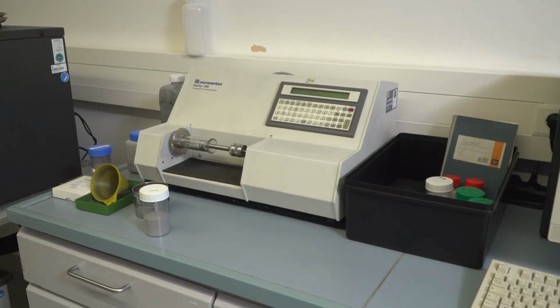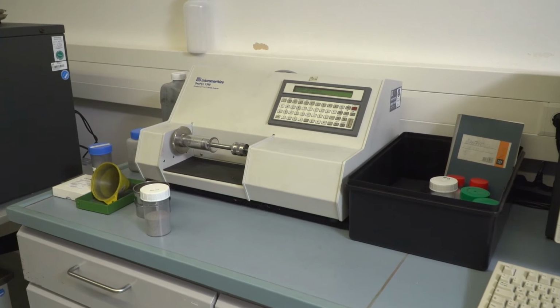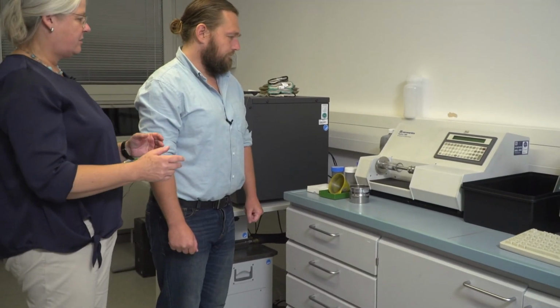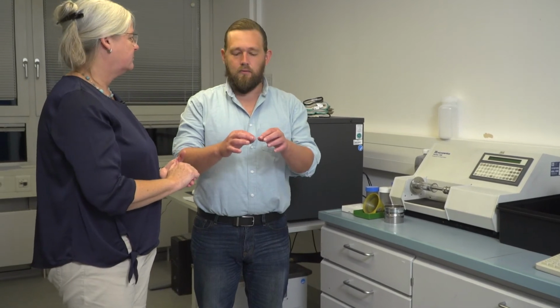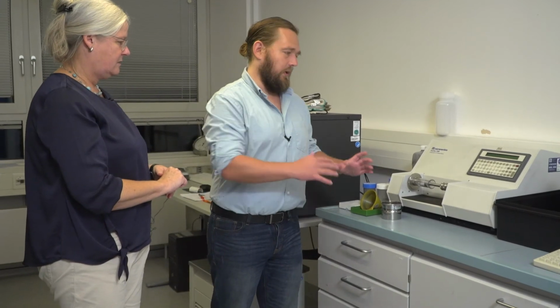So what does this device do? There we're measuring the density, the tap density or the envelope density of the particles. If you don't have a good shape where you can measure the size, you have to use this. It is just a way to see the volume of the material. So basically, if I can't measure the length, width, and height of an object, if I have particles that are all irregular shapes, you just cram it in here and it presses down on it and can measure the volume, so you can calculate the density.